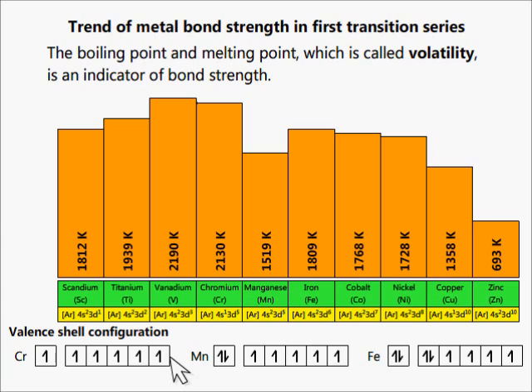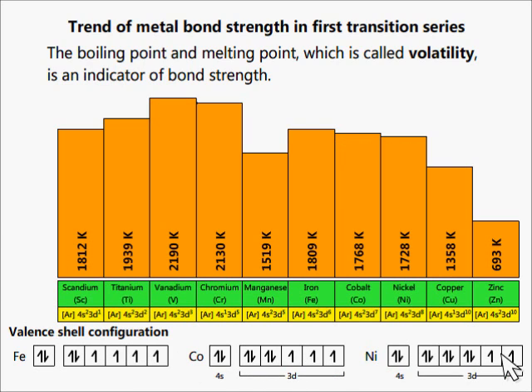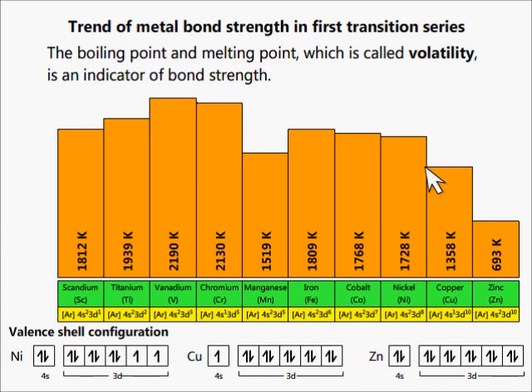This is the reason that the melting point of manganese dips further, having all the unpaired electrons in 3D subshells. From iron to nickel, the melting point decreases steadily due to decrease in number of unpaired electrons in 3D subshells. For copper, the melting point dips abruptly because the 3D subshells become fully filled. The only unpaired electron is in the 4S subshell. In zinc, the decrease in melting point is very high because it has no unpaired electrons.